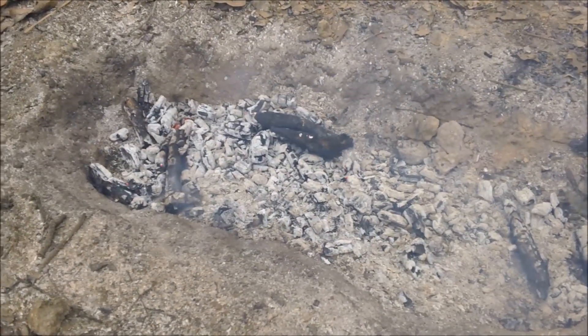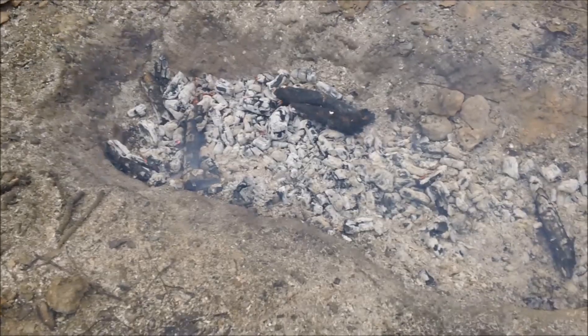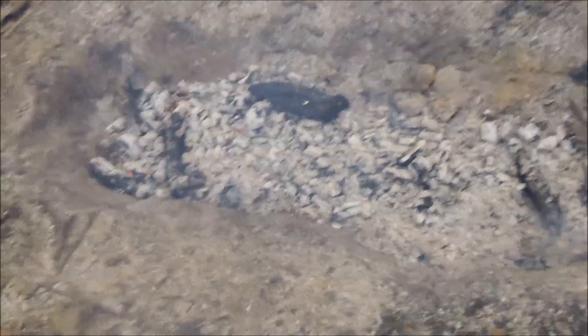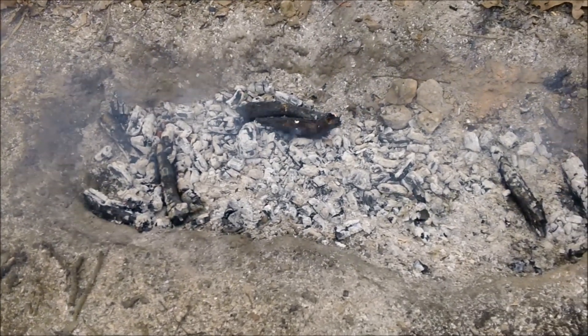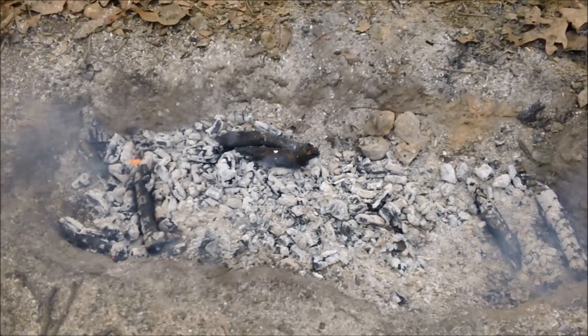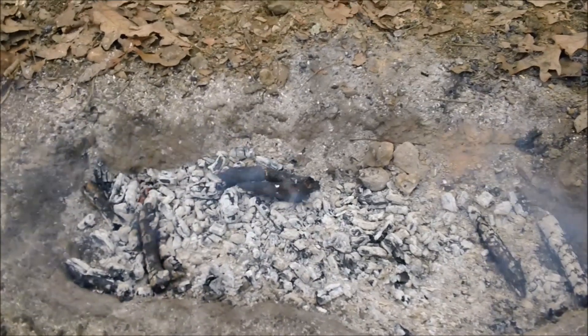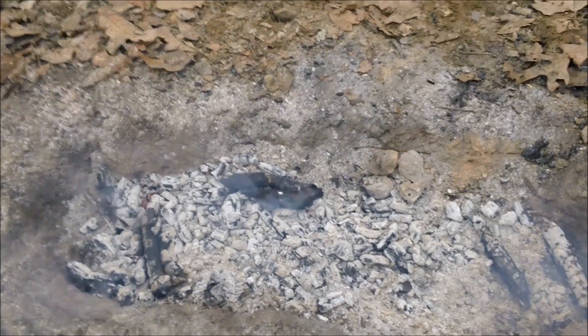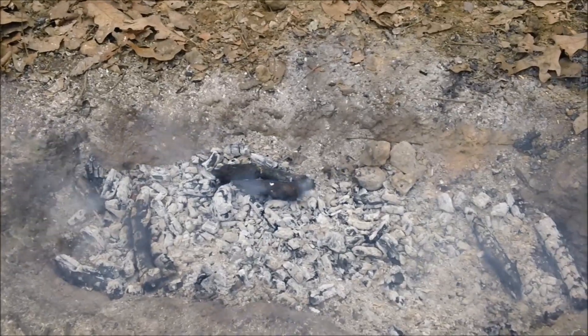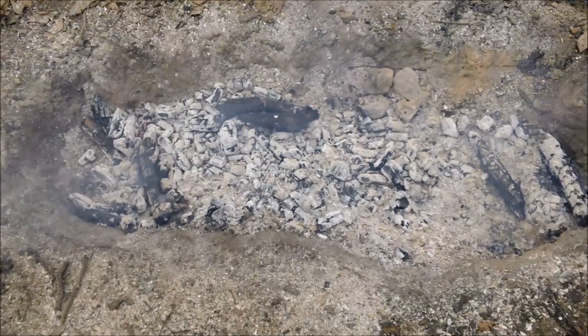This is what I mean when I say let the coals completely cover the pottery — I just wanted to show you so you get a good grasp on what it's supposed to look like. The next step is letting it cool, and that's going to take a good two or three days. You want to take your time because if it cools too fast, it's going to crack. That's when most pottery breaks — in the cooling process. I'll show you the final product after it's cooled.